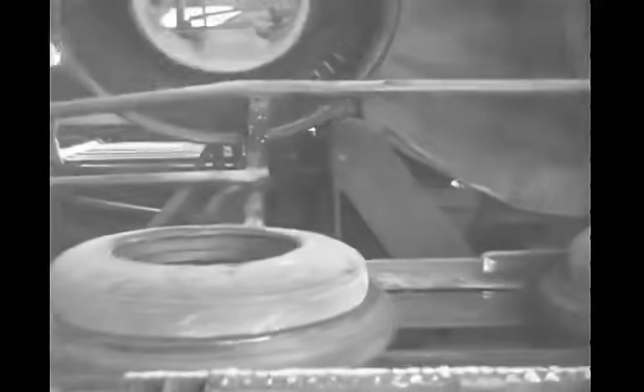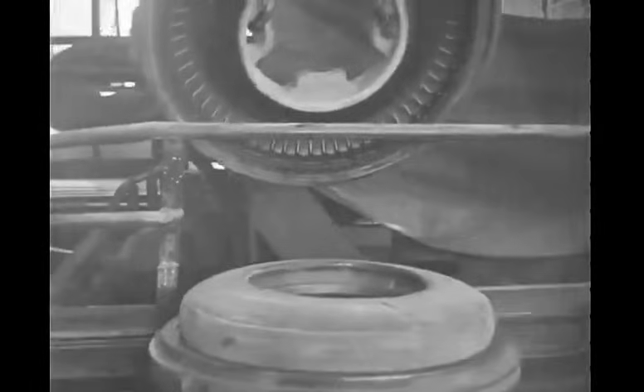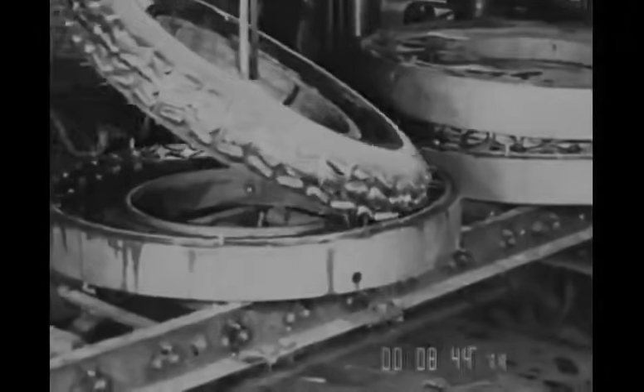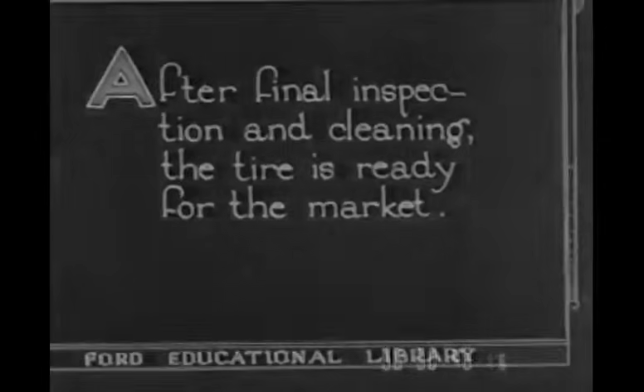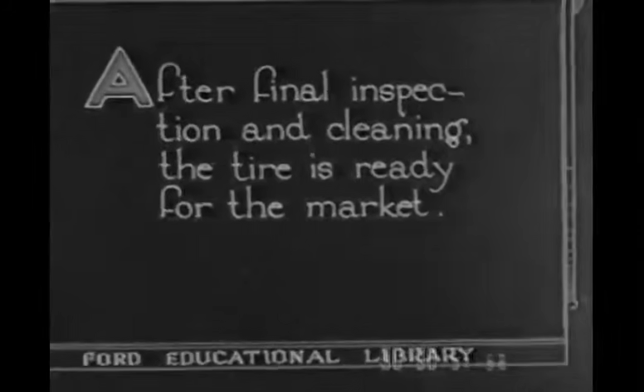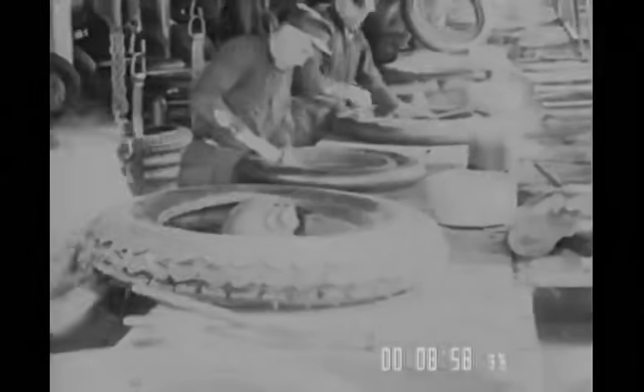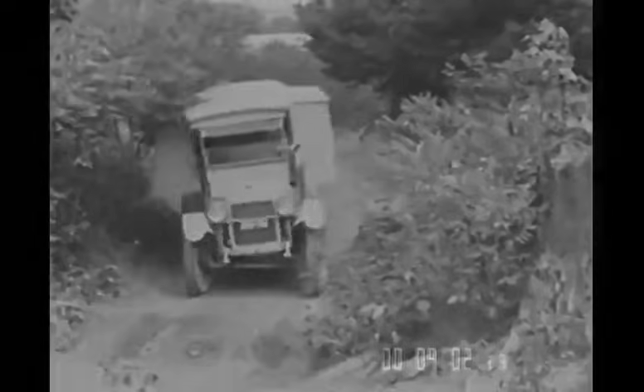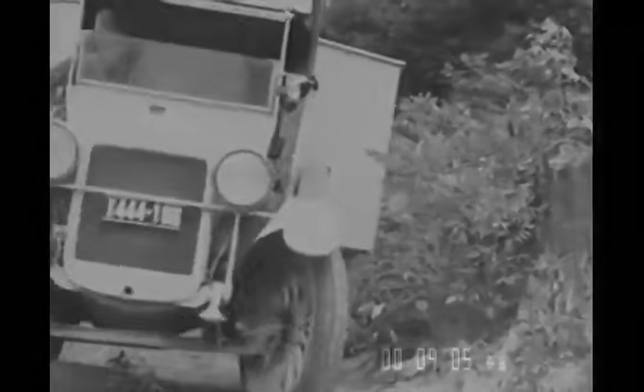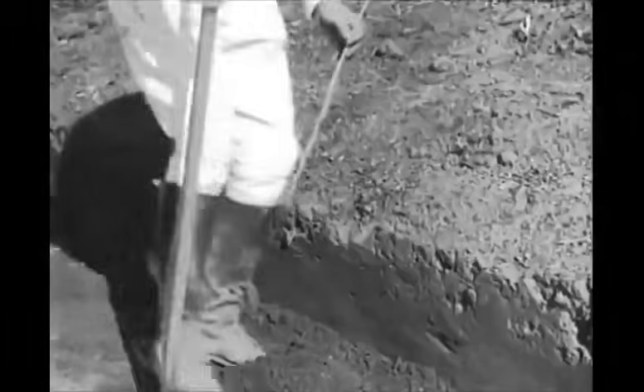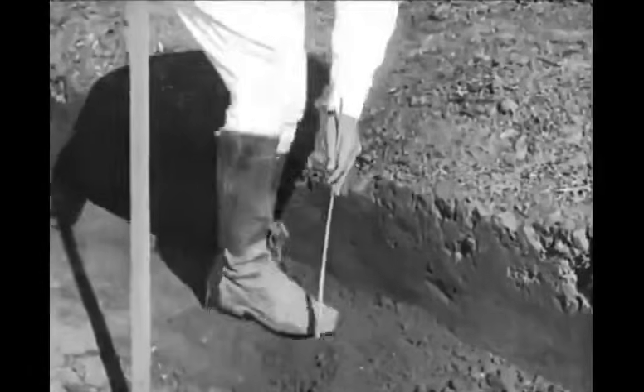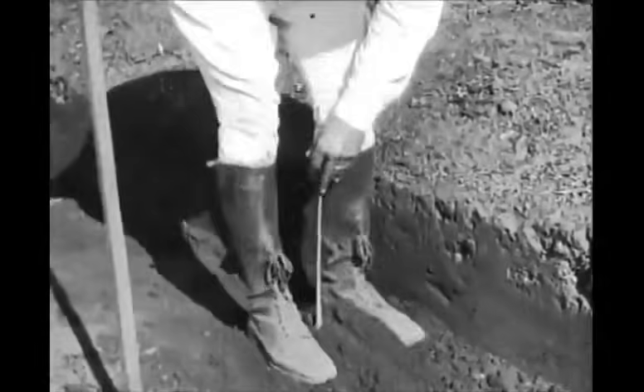Manufacturers had to change adhesives, mixing methods, accelerators, antioxidants, carbon black grades, and processing conditions. Natural rubber also handled repeated flexing and heat in ways that were difficult to duplicate. Early synthetic truck tires could build excessive internal heat. Under heavy load, flexing converts mechanical energy into heat within the rubber. If the heat cannot escape, temperature rises, bonds weaken, layers separate, and the tire can fail. Aircraft and large military tires were especially demanding. For some critical uses, limited natural rubber remained indispensable and had to be carefully allocated or blended with synthetic material.